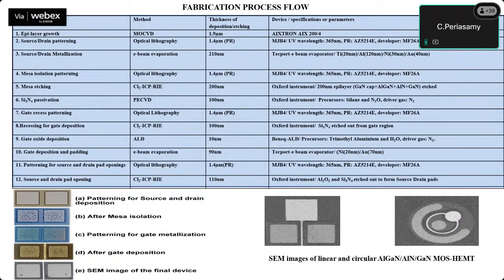That metal stack consists of titanium, aluminum, nickel, and gold. This combination of the stack we have used for source and drain in this proposed structure. We have also used mesa isolation patterning and mesa etching. To deposit the passivation layer, we have chosen silicon nitride, and the deposition method is plasma enhanced chemical vapor deposition. The thickness of that passivation layer is 100 nanometer, and the mesa etching depth is around 200 nanometer.